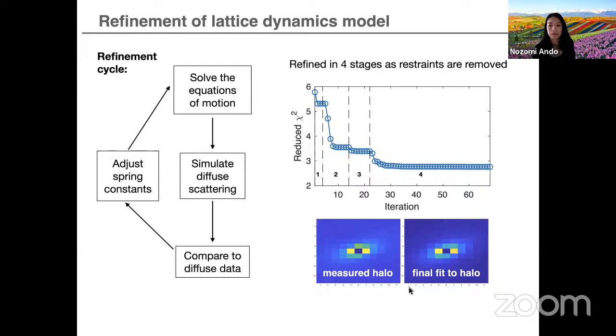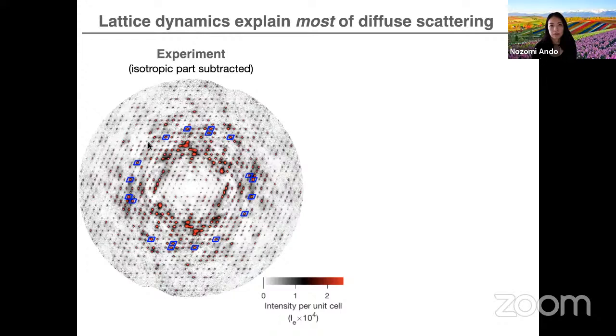So here's the result from that simulation. First of all, on the left is experimental diffuse scattering, just one slice of the Death Star. And all of the halos that are in blue boxes are the ones that were used in the fit. So you can see that they're very few.